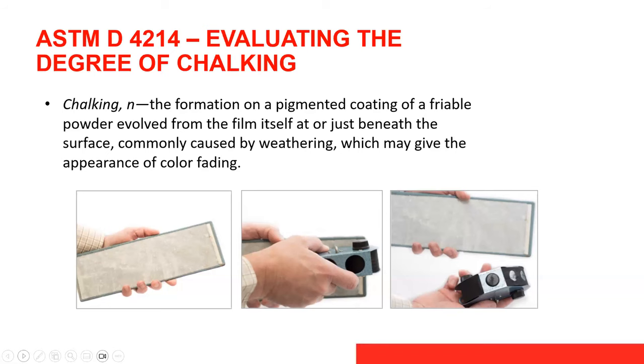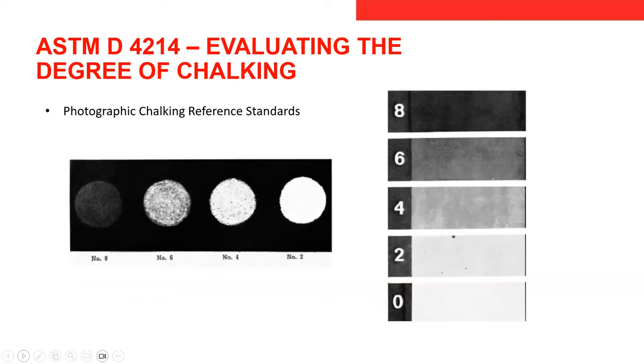And so this is a visual standard. It's often used in the coatings industry. The higher the number, the better the result. As you get lower on that visual standard, for example, the 2 or the 0, it would be a severe chalking at that point. And that's really a breakdown of the film.